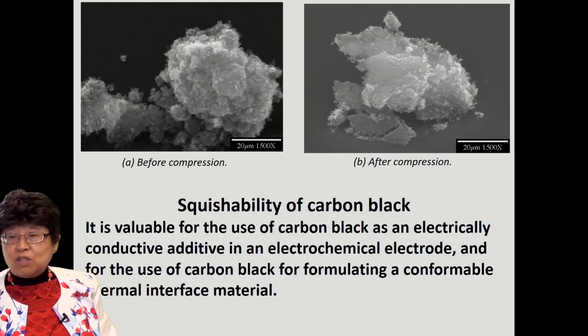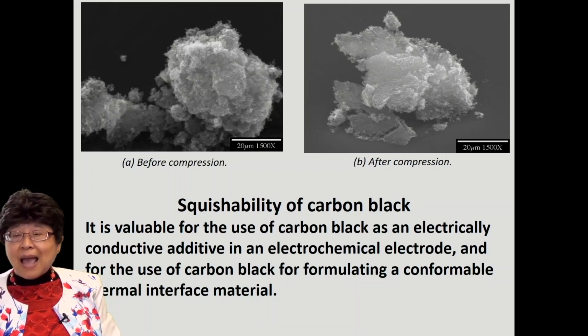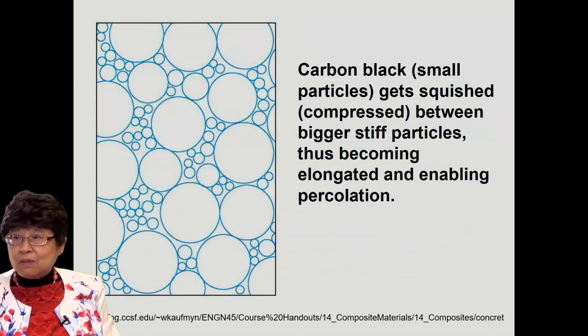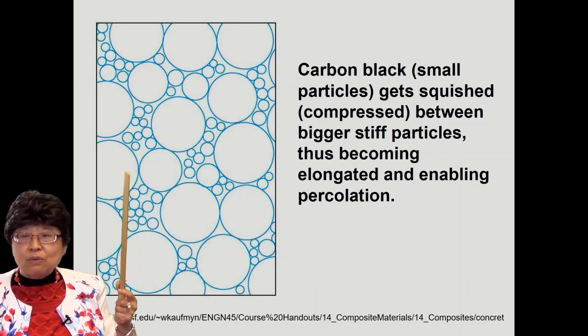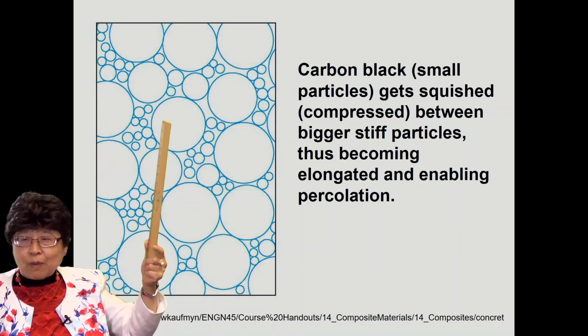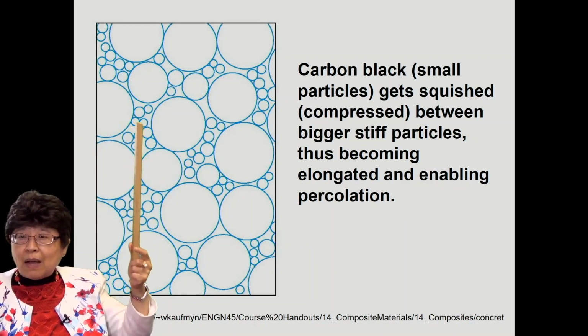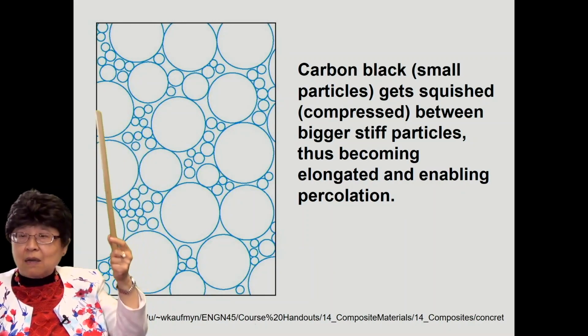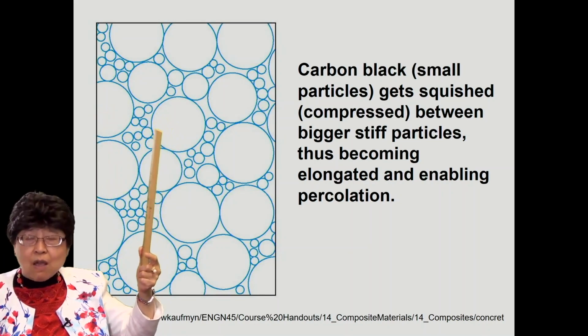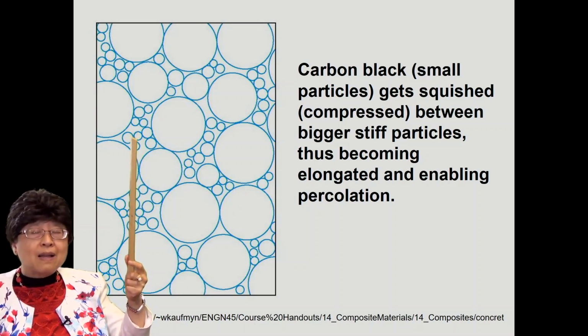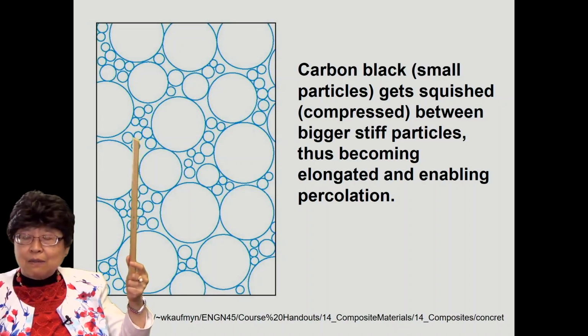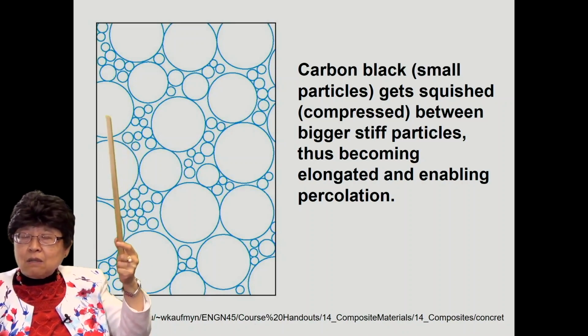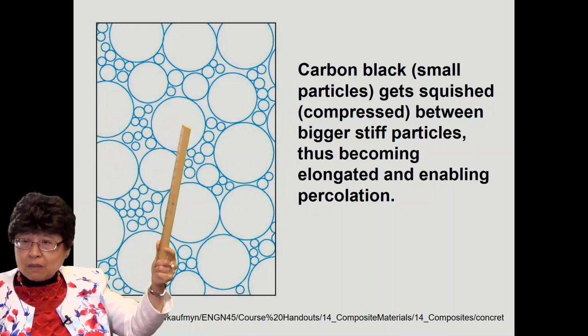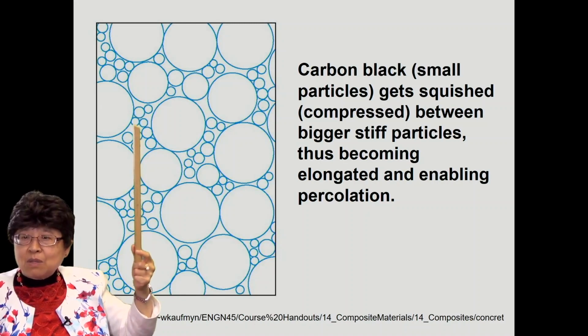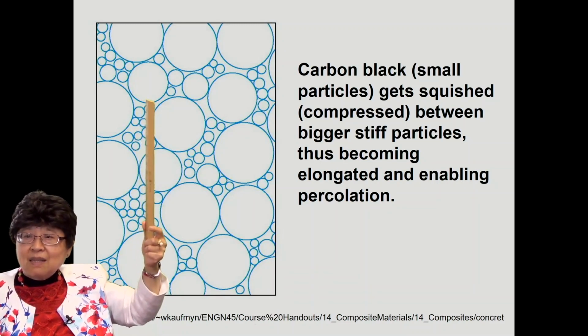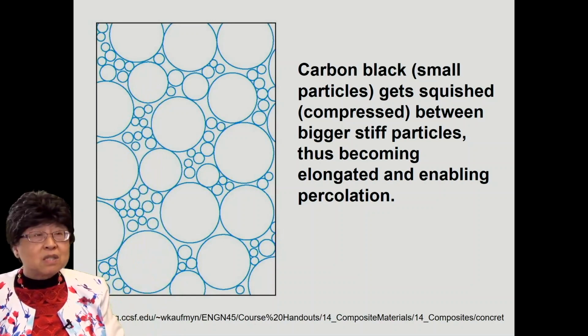In addition, because of the squishability, it is useful as a conductive additive, say in an electrochemical electrode. For instance, you have in this electrode some big particles that are needed for the electrode operation. But you need to make this thing electrically conductive because of these big particles not being conductive. So you need to put in a conductive additive to make the overall electrode conductive. And if you use carbon black as a conductive additive, the carbon black is then squished between the stiff big particles. As a result of the squishing, the carbon black becomes smeared and elongated, and so is able to touch one another, forming a continuous conductive path.